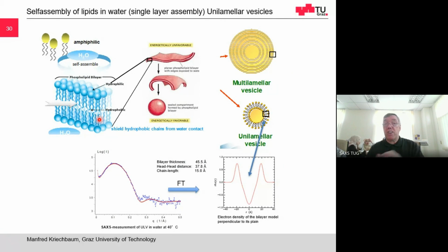So again, you can in that way produce single shell vesicles or multilamellar vesicles. If you have a single shell vesicle, you will get such a scattering curve, and from this scattering curve, you can determine the electron density of this bilayer. So here, of the single shell vesicle, the unilamellar vesicles, you make the Fourier transformation and get the electron density of the bilayer.